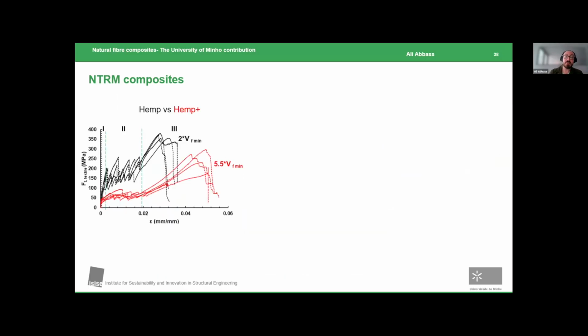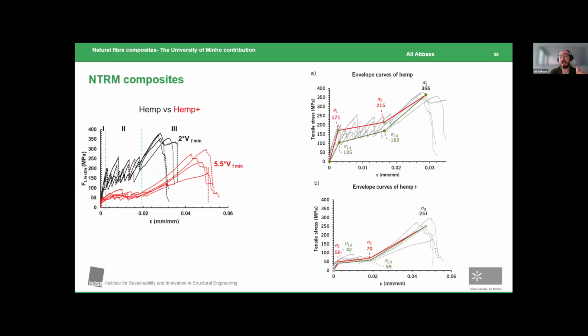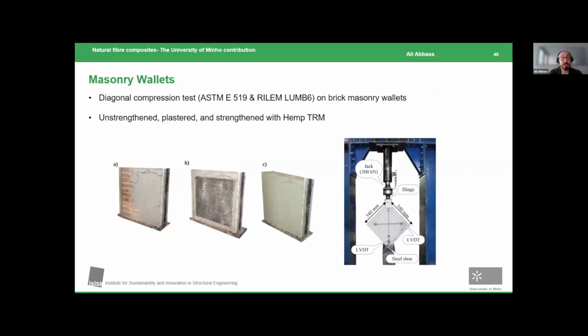And here we have the stress strain curve highlighting that increasing the volume fraction more than a specific limit is technically useless. We don't need it. And here we have the trilinear idealization of these fibers highlighting the upper bound, highlighted by the maximum stresses obtained before the bond, before failure. And here the lower bound refers to the lower values achieved after cracking immediately. So finally, to finalize, we carried on diagonal compression tests on wallets strengthened with the system developed,